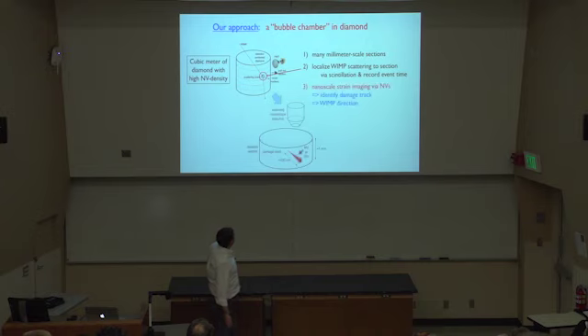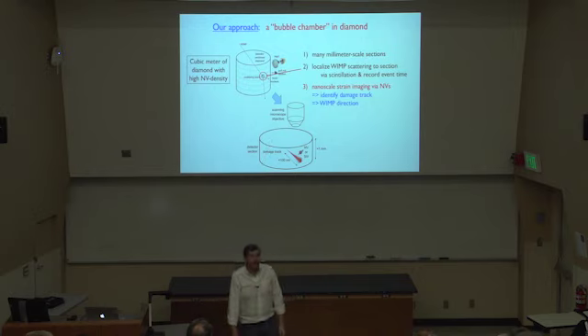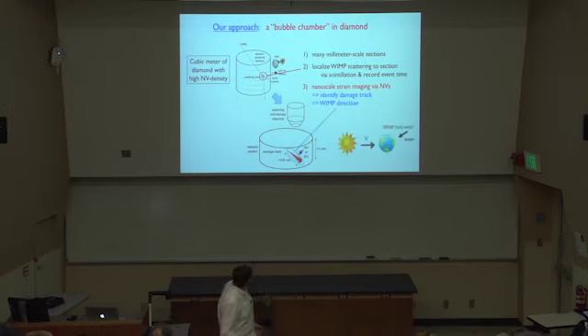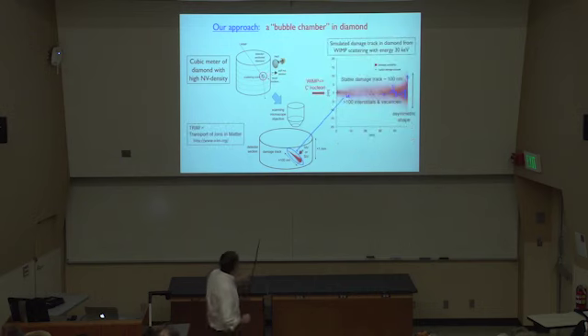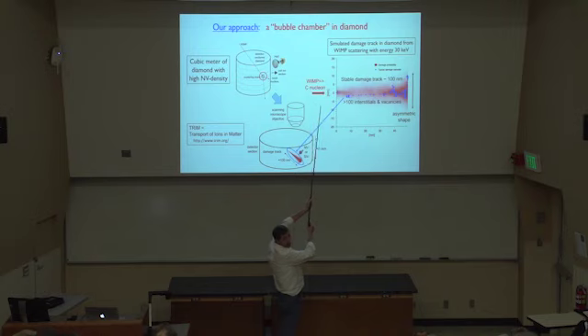Then you'd pull out that section and you'd use many NVs inside to determine the direction of the damage track. And we've done calculations as to what kind of damage track would be created, and it's something like what's shown here in this cartoon. Let me show a slightly more realistic version of the calculation. The WIMP comes in, or neutrino. It's going to, with low probability, hit one carbon nucleus. That should say nucleus, not nucleon, excuse me.